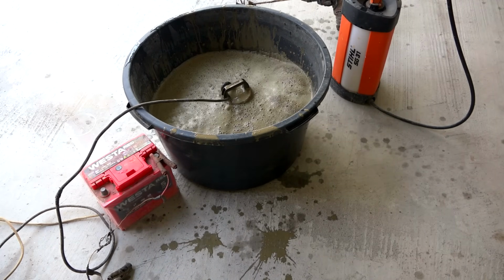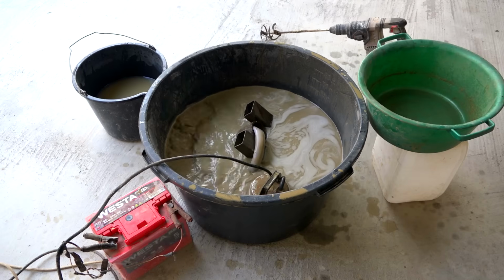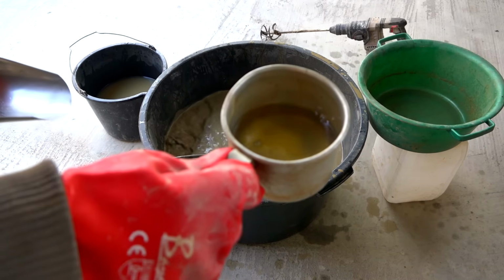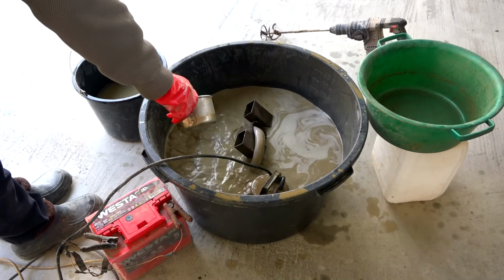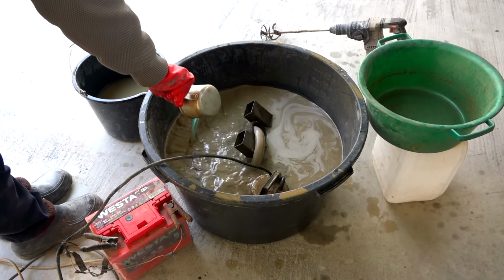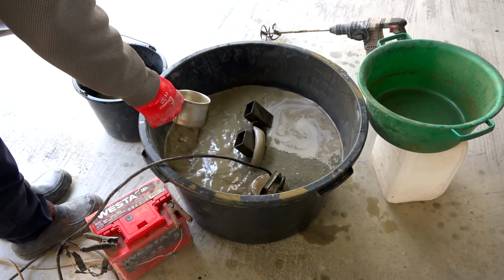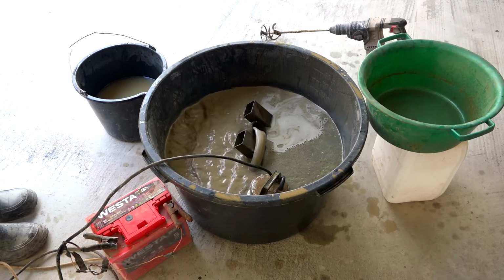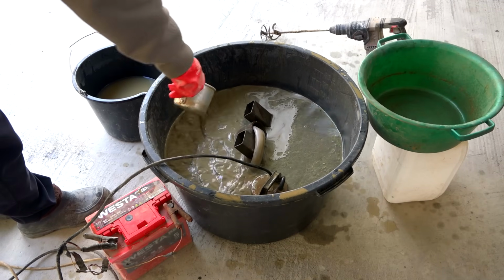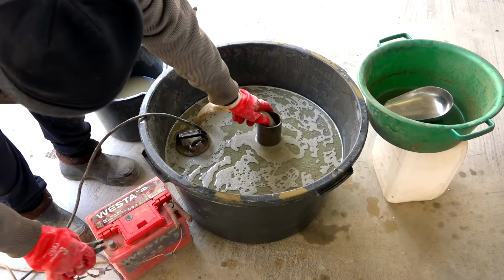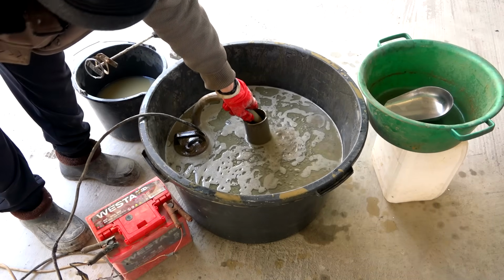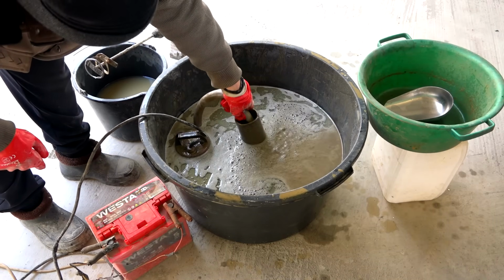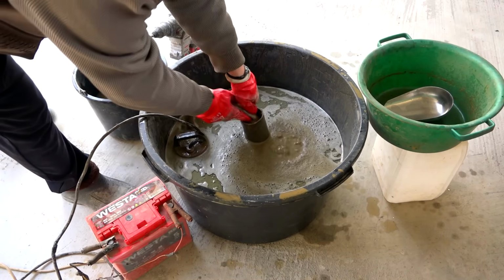This was the wrong decision. I connected the hose to the water pump and attached a weight, a piece of iron, to it to prevent splashing. At this point, I added some diesel fuel to the pulp, but the foam I was looking for didn't form. I continued running the water pump in this mode for another 10 minutes, but the buoyancy effect still wasn't achieved.